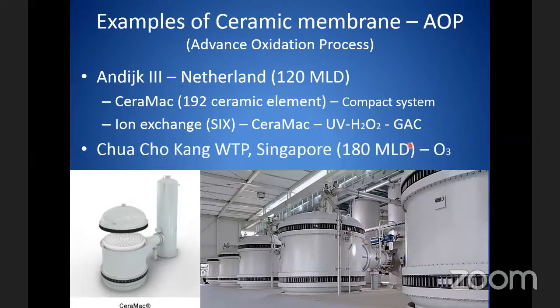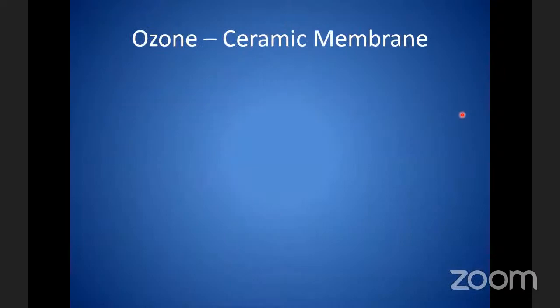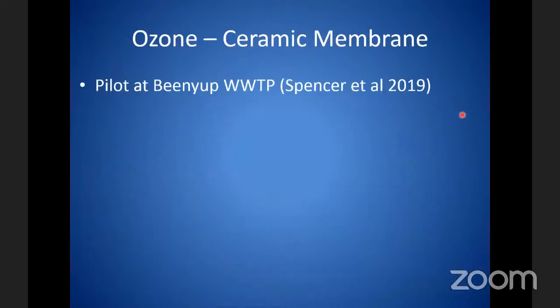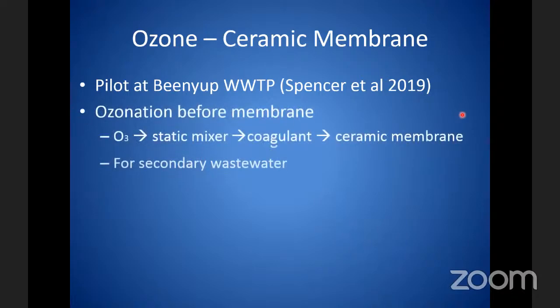So in Choa Chu Kang, when they piloted, they were using the so-called ozone before the Metawater ceramic membrane. So now they are installing 180 MLD. So ozone ceramic membrane. Recently there's another pilot done with a big configuration, the ceramic published by this Spencer. So they use O3, static mixer, coagulation, and then immediately inject into the ceramic membrane. So there may be residual ozone in the system, but it won't affect the ceramic membrane.